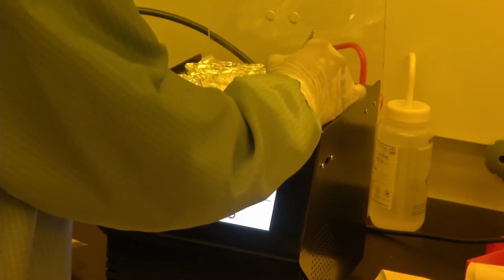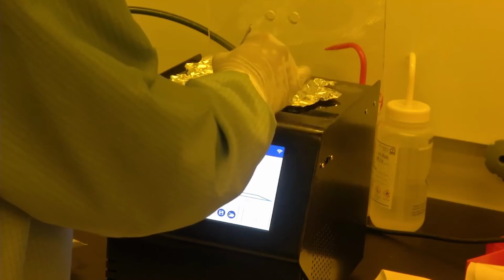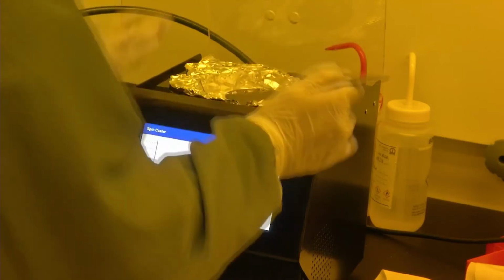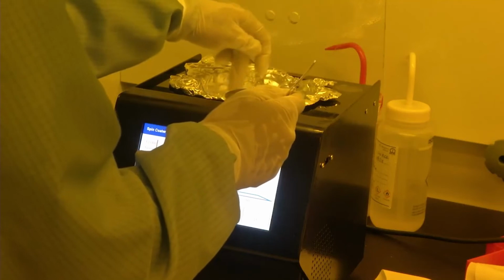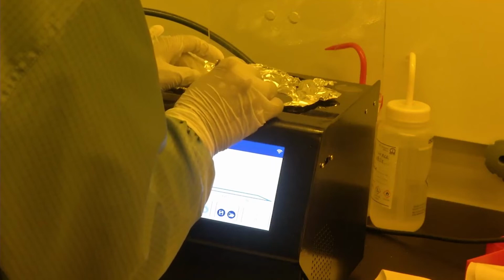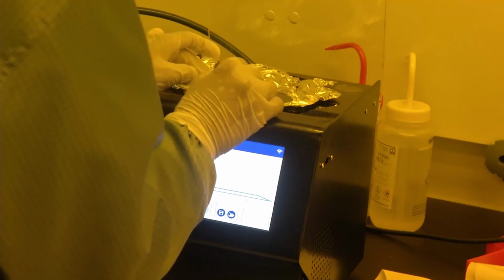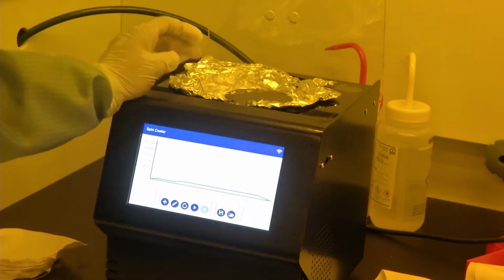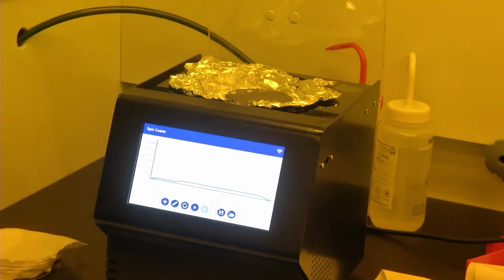We need to align the vacuum chuck with the silicon wafer to ensure that the centrifugal force acting upon the silicon wafer, which ensures uniform coating of precursor or any other photoresist, matches with the central axis of the vacuum chuck. Once that is done, we are ready to let the silicon wafer be held by the vacuum chuck. For that we have a dedicated pump. My colleague will switch on the vacuum pump and you will hear a noise coming out of the pump.